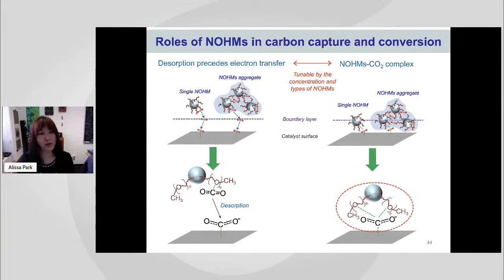Another interesting thing was when we looked at the selectivity, Faraday efficiency of these reactions, they were a little bit different with and without NOHMs, which means that in our hypothesis, there are two modes of CO2 delivered to the surface of the catalyst. Left-hand side is showing how NOHMs becomes an internal reservoir for CO2. You can increase the solubility of CO2 by having all this complexation or sorption along the polymer chain, and eventually that CO2 sorbed onto the NOHM space can be dissolved and then absorbed onto the surface of the catalyst.